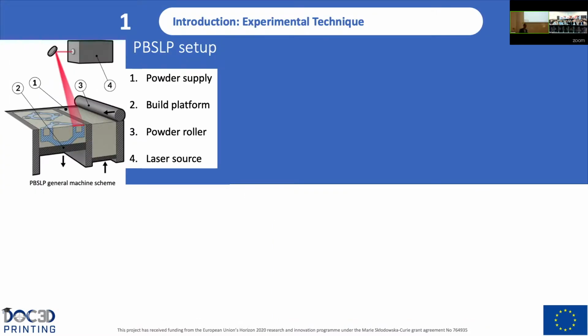So regarding the setup of this technique, here we can see a general setup. The ceramic is in powder form and moves towards here, where a powder roller picks up the powder, and the powder is spread onto a thin layer on the build platform. Here there is a laser which scans the powder selectively, following a pattern determined by the software of the machine.